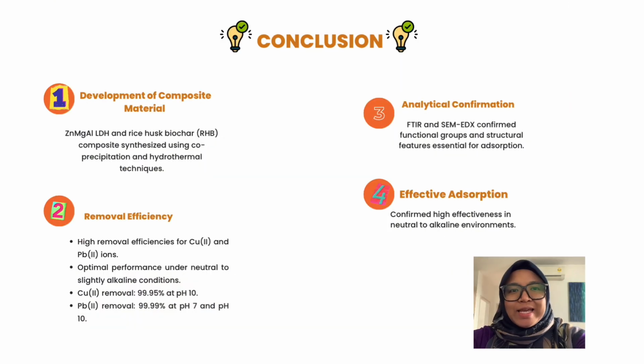To conclude, this study successfully developed a novel composite material combining zinc, magnesium, aluminium LDH, and rice-husk biochar for the effective removal of heavy metals from synthetic wastewater. Our results demonstrate that this composite material is highly efficient in adsorbing lead and copper ions, significantly reducing their concentration in water. The combination of LDH ion exchange properties and biochar high surface area creates a synergistic effect that enhances the overall adsorption capacity.